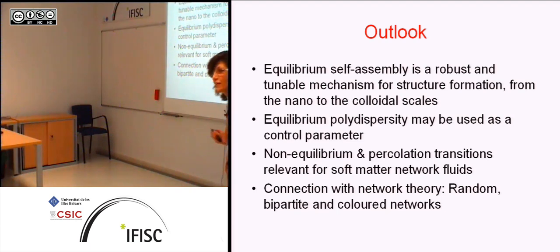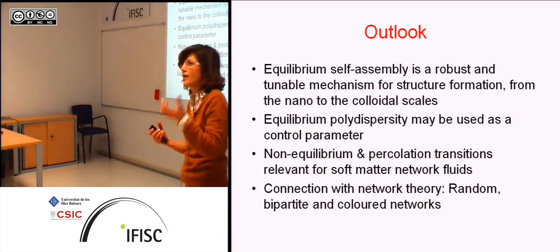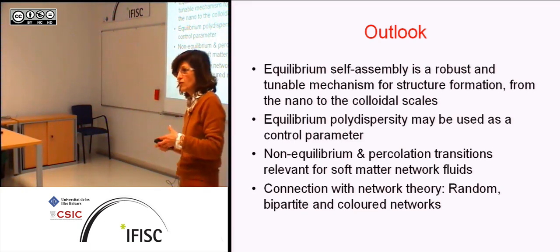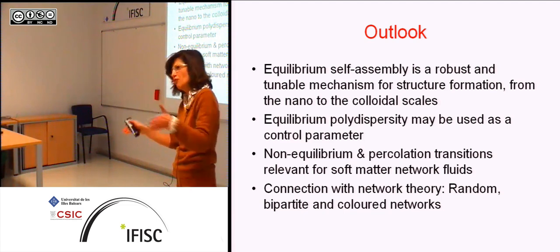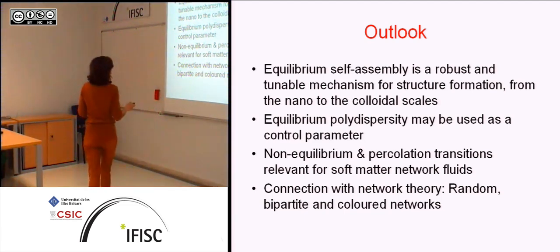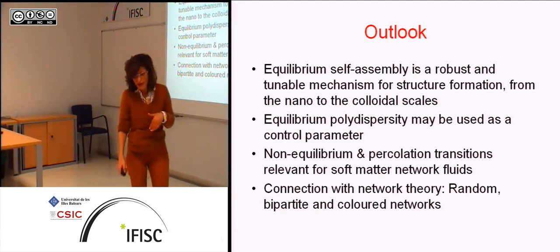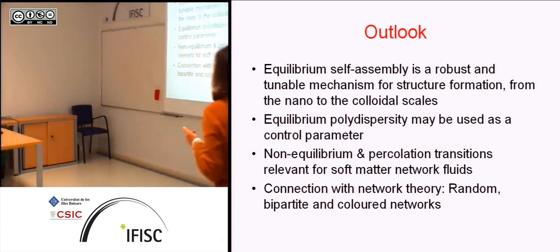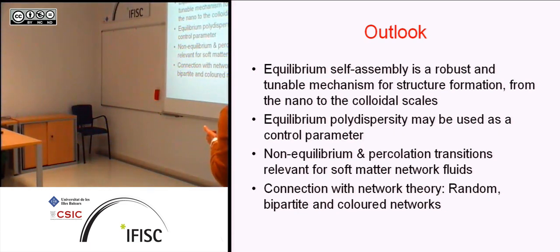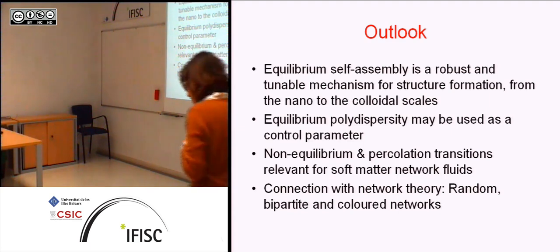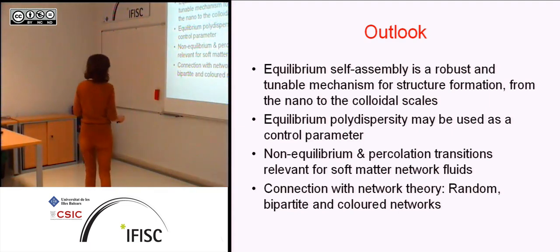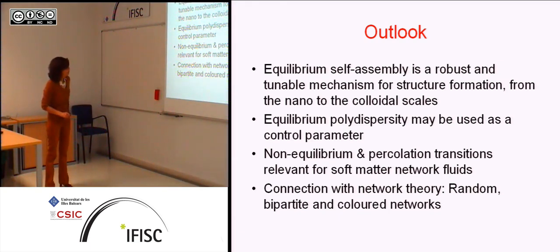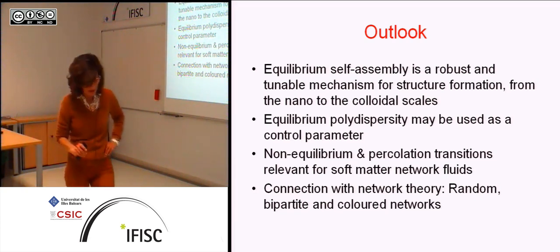And you can get them, if you forget the time scale, what I said is kind of relevant at the atomic scale as well as at the colloidal scale. So this is a mechanism that works for a large range of particle sizes. The polydispersity, rather than be looked at as some nuisance, can actually be very useful to control some of the structures of these systems. I think it was also clear that non-equilibrium and percolation are things that are very relevant if you want to look at these network fluids. And finally, I want to say that there's a very strong connection between quite a few, all of the things I said and network theory. The system with equal sides, the distributions, the percolation, and so on, can be mapped exactly to random networks.